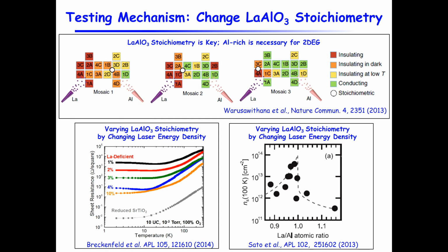And there's a paper from Lane Martin's group. They also studied the oxygen stoichiometry. And here is from Harold Hwang's group. In each of these cases, they change the stoichiometry by changing the laser energy density. But if you are changing the laser energy density, the bombardment situation is different, and the properties of the film are not just from the difference in stoichiometry. So these are the works that one can find in the literature that studied the effect of stoichiometry.